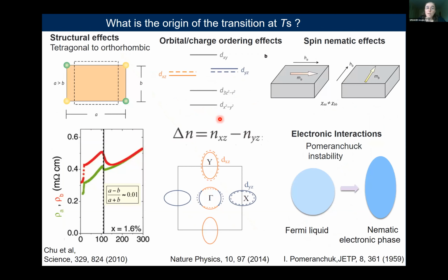So now the nature of this structural transition before the system becomes magnetic is under a lot of debate, because we can have a few different potential candidates. First of all, it could be that the lattice plays an important role, and we have a tetragonal to orthorhombic transition due to the interaction with the lattice. But the studies of transport anisotropy show a very large difference between a and b direction, much larger than one could predict based on the changes in the lattice parameters.